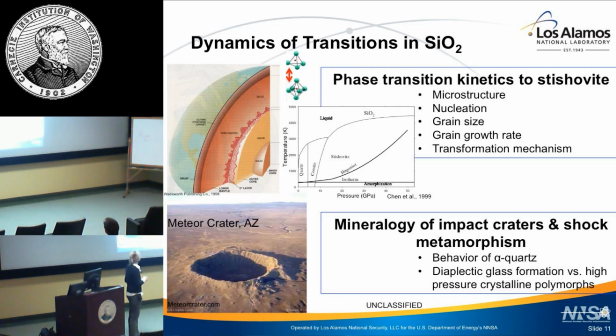Now, SiO2 has been well studied in both the static compression community and the dynamic compression community, but for the first time, we'll be able to explore the phase transition kinetics of SiO2 transforming to the high-pressure polymorph stishovite. We're going to look at nucleation time, grain size, and grain growth to pull out the phase transition mechanism. How does it transform? Then we'll also look at a real rock former. We'll look at alpha quartz transforming to stishovite to give more context between what we find in the field at an impact site and what we can find in the laboratory. So we're trying to make a correlation between the laboratory and the field.